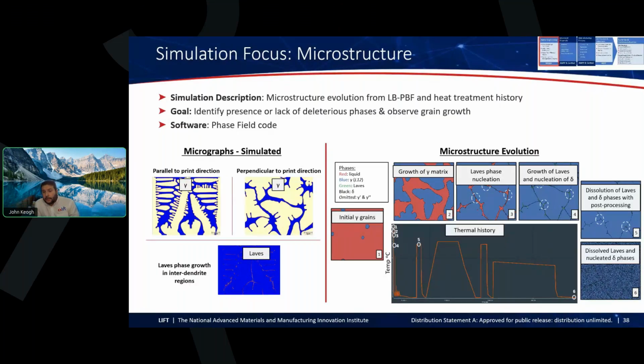And we actually got very good agreement, pretty much across the board. So we were quite pleased with that. But it doesn't always work. The same is true for crystal plasticity. For instance, if you're talking about property prediction from microstructure, it works for some crystal structures and not well for others. But either way, we were very pleased with this.